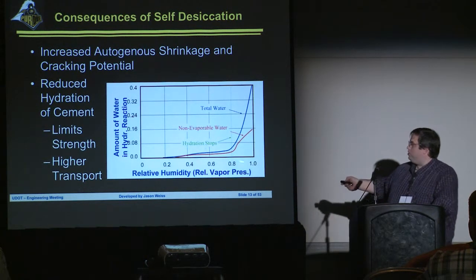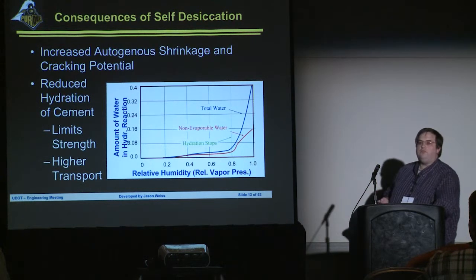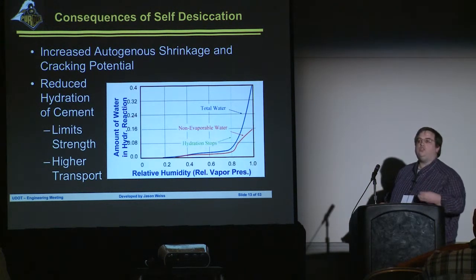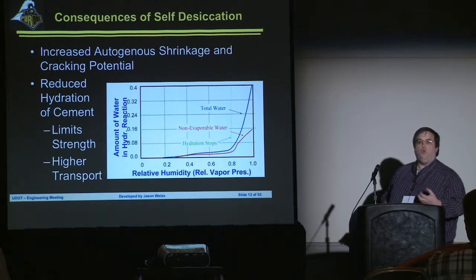In addition, as these vapor-filled spaces start to form, we start to reduce the relative humidity inside of our concrete. We actually reduce the pore pressure inside of our concrete. We make the water less chemically active in the system, which means that it's not able to hydrate as much of the cement.